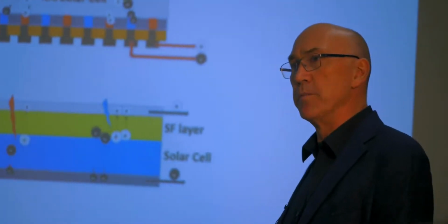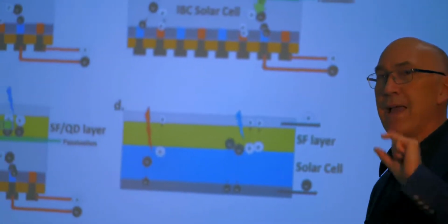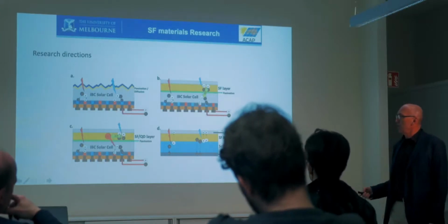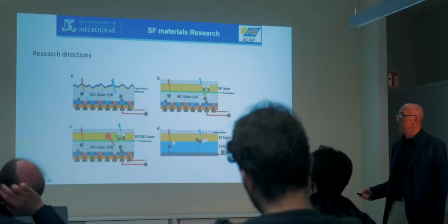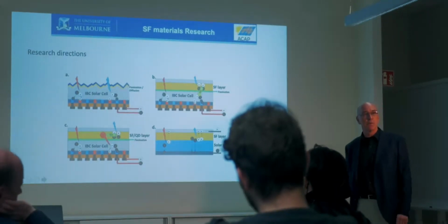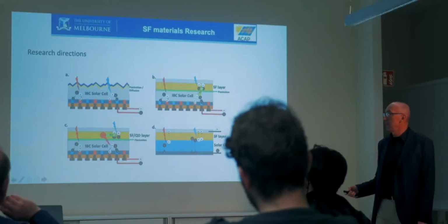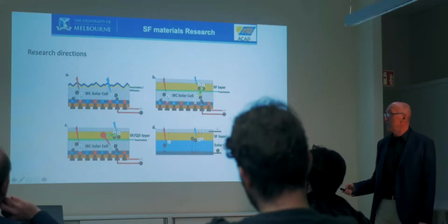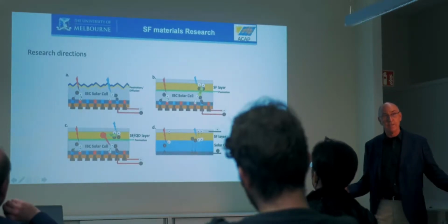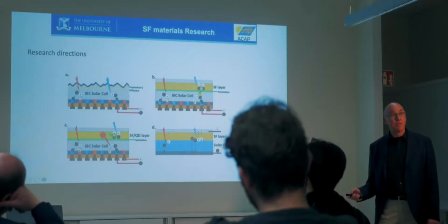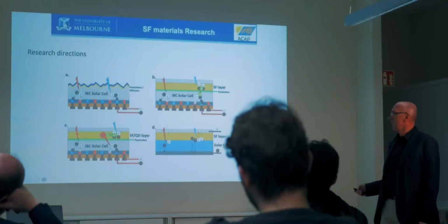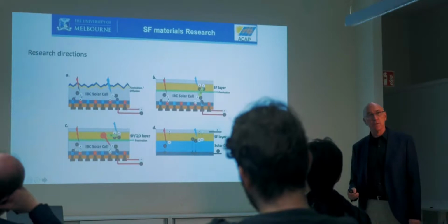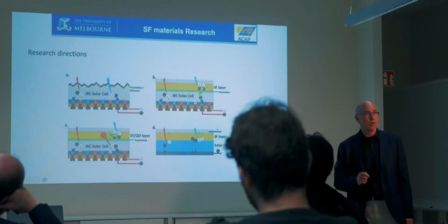Okay, so this is what people have demonstrated before, but they had a very, very thin film and really poor light absorption. People also do a similar thing. They take the triplets and transfer the energy to something which is going to emit light, so a quantum dot or something, and then that light is reabsorbed. The trouble is your singlet fission has to be very efficient, your transfer of energy has to be very efficient, and your emission from your quantum dot also has to be very efficient, knowing that as soon as you do this emission, 20% is going to be lost through the top of the solar cell. So people are doing that, but the trouble is you have so many loss pathways. What I'd ultimately like to do is actually incorporate the singlet fission material into the solar cell. But that has its own problems.